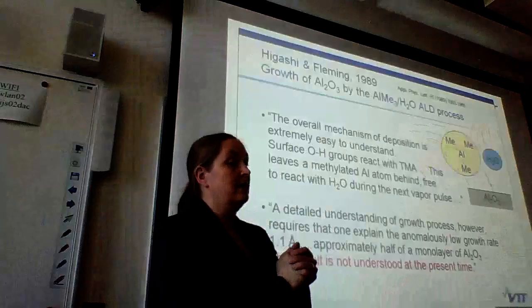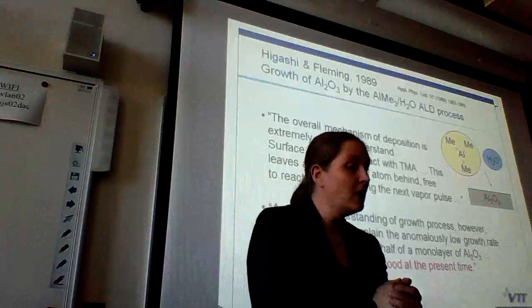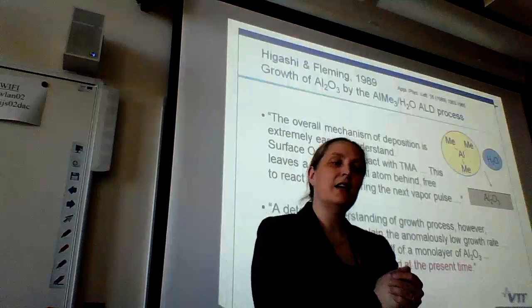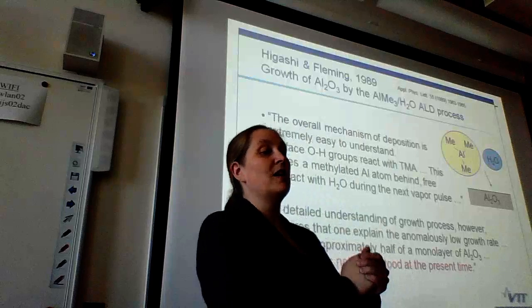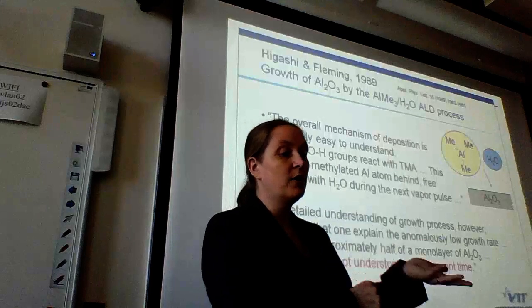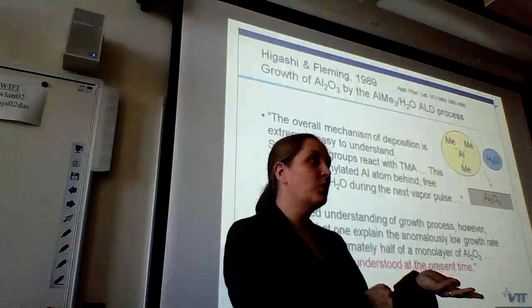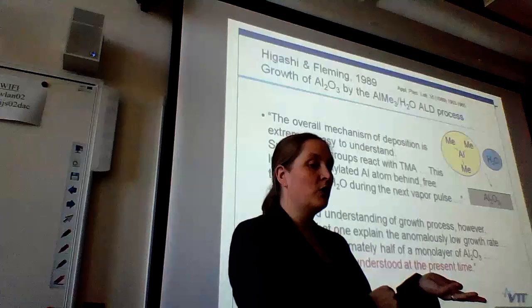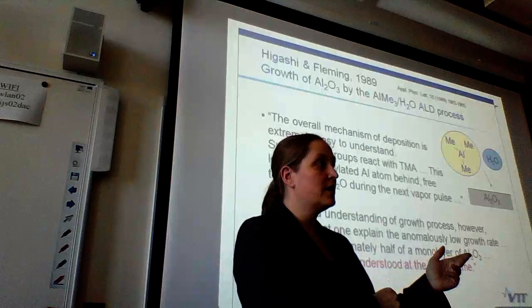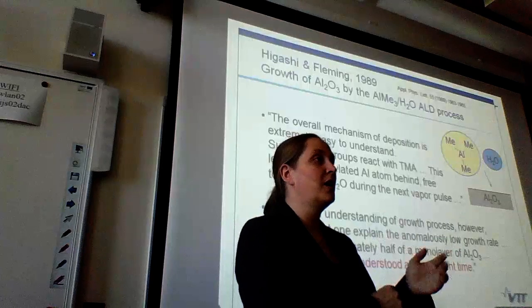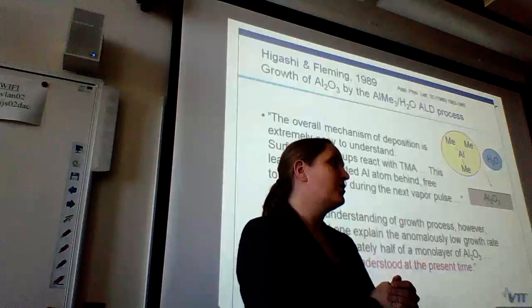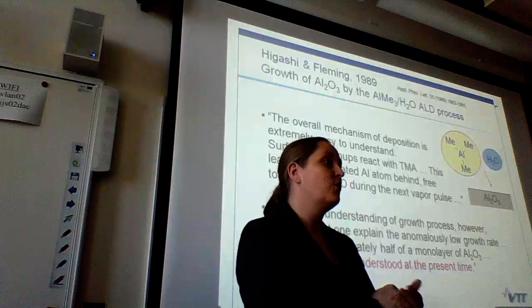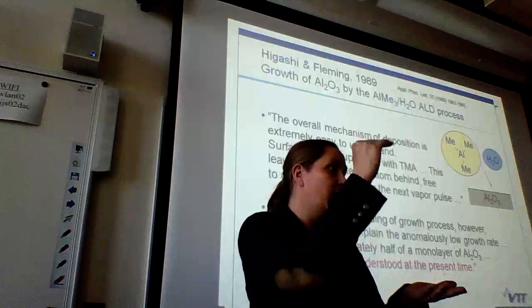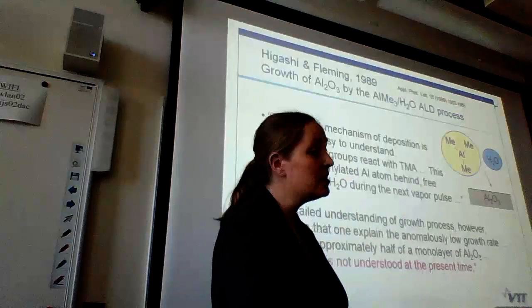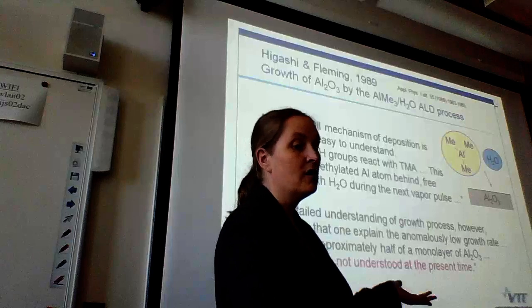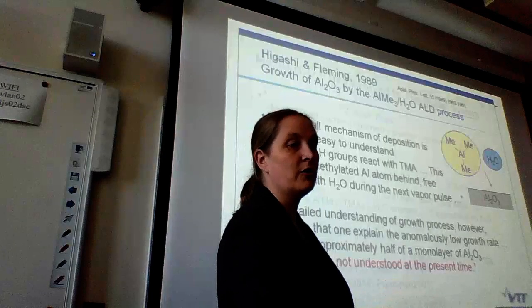A detailed understanding of the growth process, however, requires that one explain the anomalously low growth rate, 1.1 ångström, approximately half a monolayer of aluminum oxide. This result is not understood at the present time. I don't think that it became understood in the schemes either that we saw. They showed a monolayer growth per cycle, but it's not a monolayer. It's about half or 30% of a monolayer.